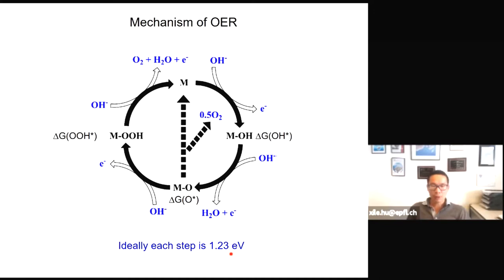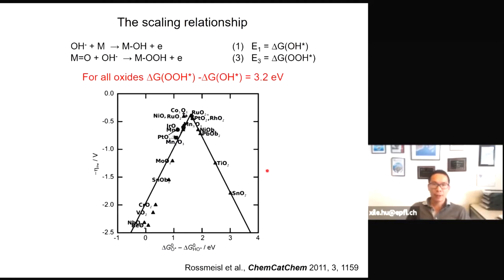This is ideal but not practical because it has been shown that various adsorbed species, and this is not unique to oxygen evolution but to many heterogeneous reactions, have a so-called scaling relationship in their energies. For instance, in this case, the adsorption energy difference of hydroperoxy and hydroxy species on all metal oxides is about 3.2 eV, and that is not the 2.46 eV if you follow the ideal thermal cycle. And that gives rise to so-called